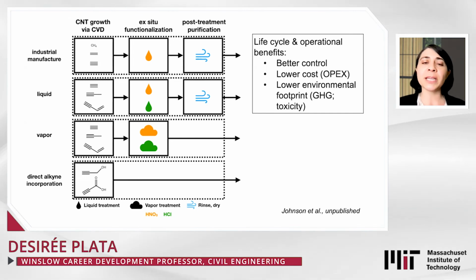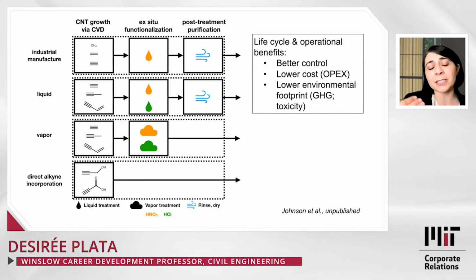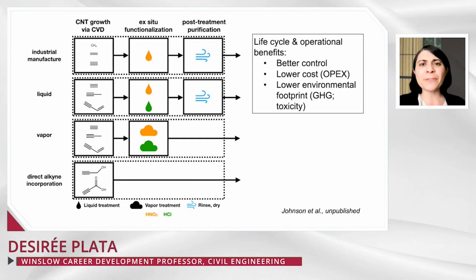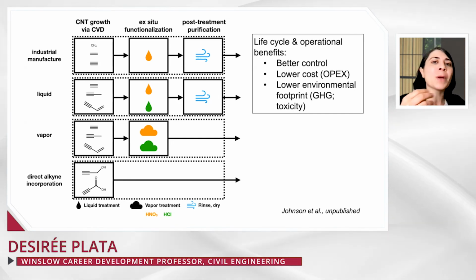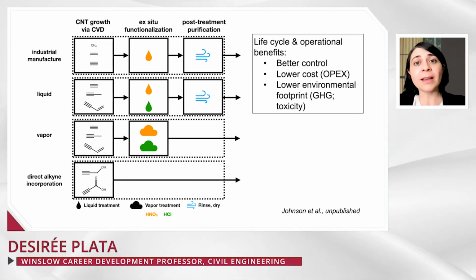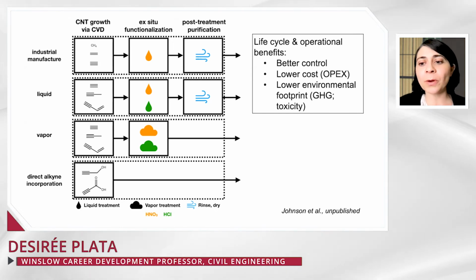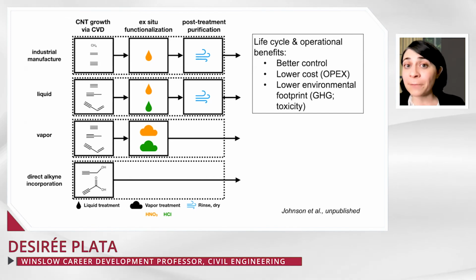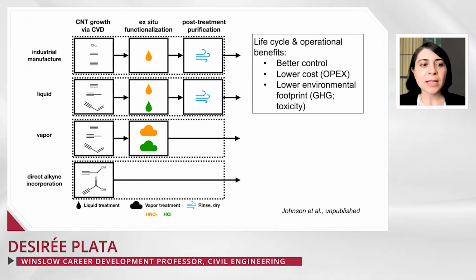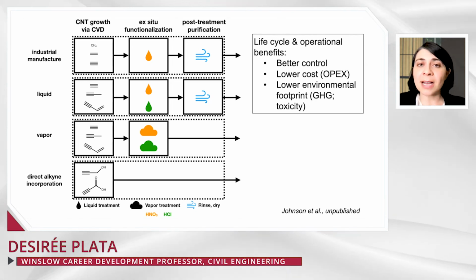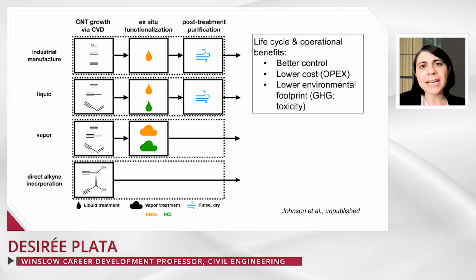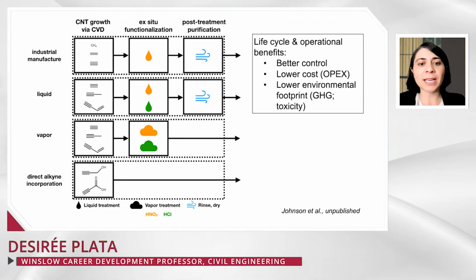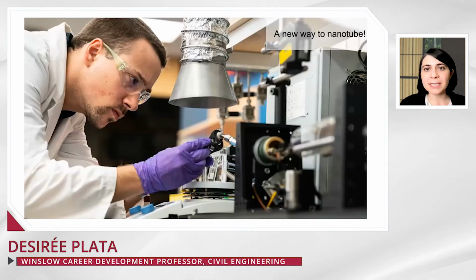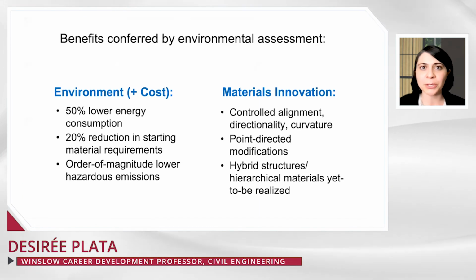Now, the idea that I'm trying to show here is that in industrial manufacture, when you want to get an oxygen group on a carbon nanotube, you might reflux it in hot acid for a long period of time, wash it, and then do some subsequent chemistry to try and get the groups that you want in the places that you want. It tends to be quite random, actually. We tend to only add oxygen groups where there are defects in the forest structure and not where we want them. The idea here is to actually just directly add the alkynes where you want them to be able to give you a molecular handle to be able to add other subsequent chemistries. So this is a very exciting advance. We think this is a new way to grow nanotubes, and this is Eric Johnson, the student who was responsible for most of the work I just showed you.